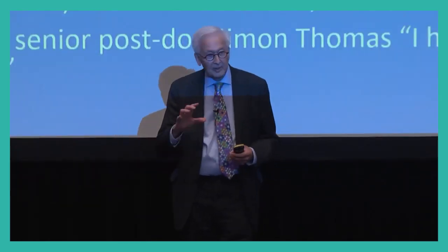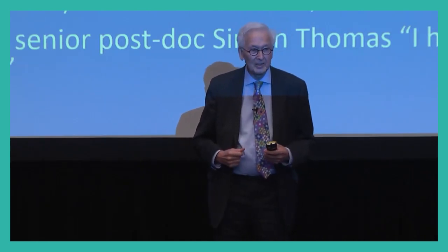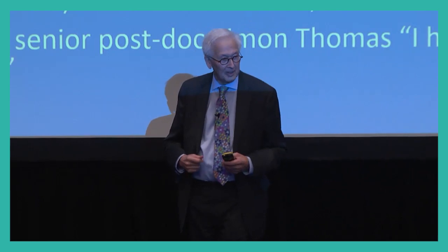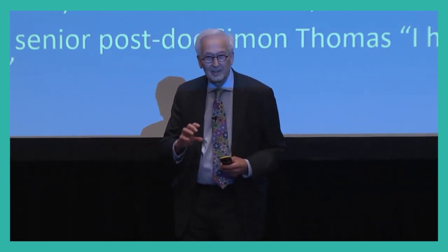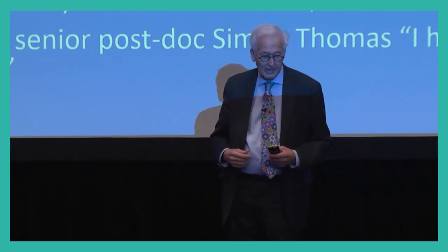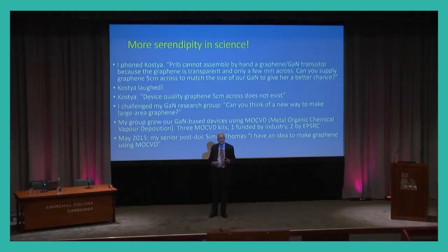And so I then had my weekly gallium nitride research group meeting. And I said, can anyone here think of a new way to make large area graphene? Because CVD graphene isn't really good enough to be making devices. And so as it happened, my group was growing gallium nitride based devices using a technique not called CVD, but called MOCVD, which is metal organic chemical vapor deposition. And I had in my group three of these kits of MOCVD, one funded by industry and two funded by the EPSRC. And a month later, I had a senior postdoc in my group and he said, Colin, I have an idea to make graphene using MOCVD.